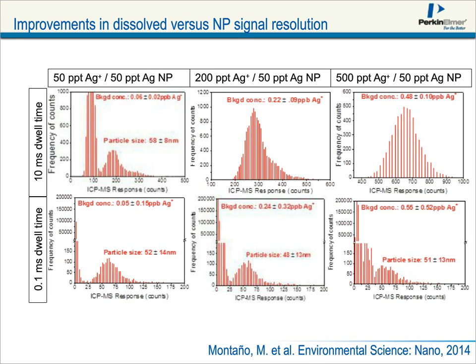As you can see, as you go to the right, if we take the same amount of nanoparticle silver and increase dissolved silver, at 10 milliseconds, we quite quickly lose that nanoparticle signal in this large background. But with the 100 microsecond data collection, we still are able to resolve particles on these higher backgrounds. And as Kevin mentioned, you combine the two techniques, the ion exchange and the short dwell times, and you may improve this even more.